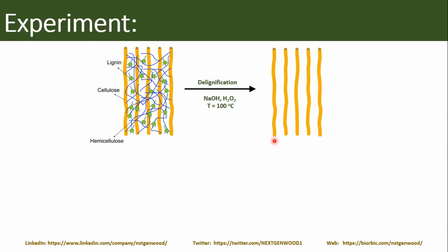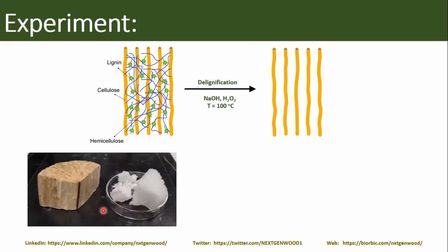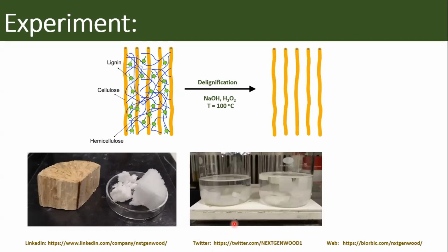So just a few pictures. That's, for example, a log of natural wood. And this is a piece of cellulose we produced after treatment. As you can see, if we do it carefully, we can preserve even the shape of the log. So it does not break and fall apart like it happens when we produce paper, for example. And this picture shows, unfortunately, it's not very well seen, but you can see these are actually our membranes, which we can produce in the same way. So we can cut wood in certain shapes like square, rectangular, anything. And then we can carefully delignify them and produce this white and nice looking cellulose membranes.